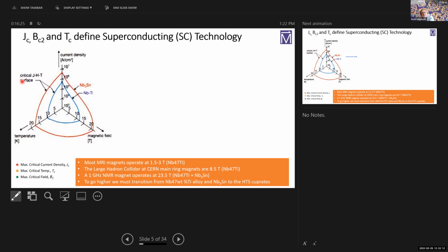Now, from the point of view of using these things, basically the killer app for superconductors is the creation of very strong magnetic fields well beyond anything you could do with the saturation of iron, or in large volumes where you may require 1.5 Tesla in a very large volume, and the I squared R dissipation losses in the copper windings, which are saturating the iron, may be very expensive in energy. Of course, many electric motors now operate with strong permanent magnets, but nevertheless, you are limited there to rather low magnetic fields, down in this portion of the diagram.